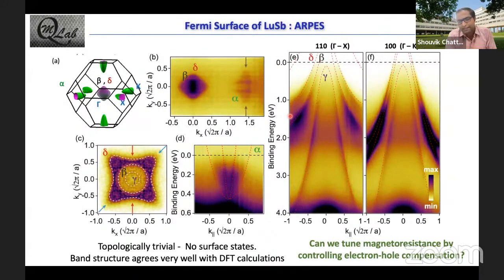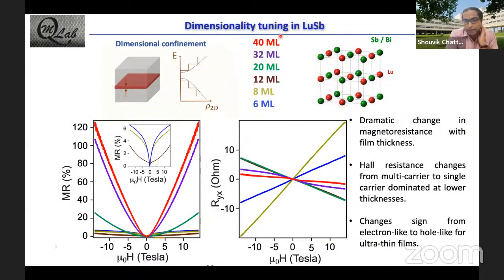Now, this is what you would be able to do also using bulk single crystals, although there is some difficulty in cleaving this material because it's a three-dimensional system, but still you can do what I have shown. But we wanted to take a next step forward and ask, if your understanding is really correct, can we now really control this electron hole compensation and try to see if we can tune the magnetoresistance? And we will utilize here the technique of dimensional confinement. What we will try to do is thin down our thin film, because it is a design choice, so we can create materials of arbitrary thicknesses. And when we do that, we find that there is a very dramatic reduction in the magnetoresistance, and in the very thin limit, it actually starts to saturate.